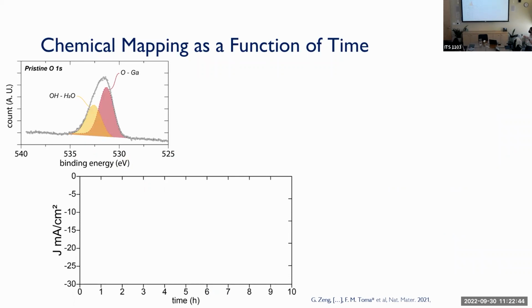So we did the X-ray photoelectron spectroscopy, and in this case, you're looking at oxygen 1s. You just look basically at the composition and the oxidation state of the different elements in the material. But here you're mostly looking at oxygen. And this is the oxygen 1s of the pristine material. You have the oxygen bound to the gallium, so this is just by adsorption. Because you have gallium nitride, you shouldn't have oxygen, right? But then because you're exposing your sample to air, there can be water that adsorbs, there can be oxygen that adsorbs, and that's why you see it. And in fact, we see the oxygen bound to gallium, but also the hydroxyl groups because of water adsorption.